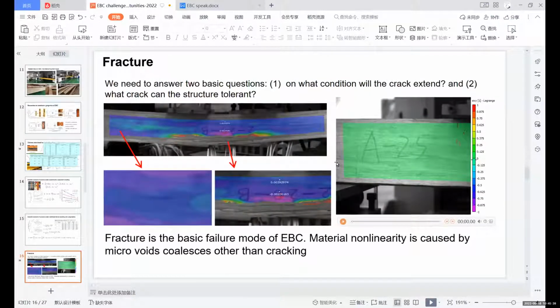So the other challenge is the fracture. So we need to answer two basic questions: on what condition will the crack extend, and what is the crack tolerance of the fracture? So this video shows the crack processing of the bending members. It shows the crack in the middle depth of the bending shearing segment, cracking along the fibrous direction. So please, the video doesn't work in this mode. I'm sorry. It shows the process of cracking generating and developing in the bending shearing segment.